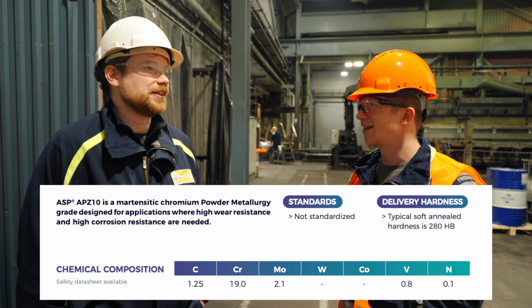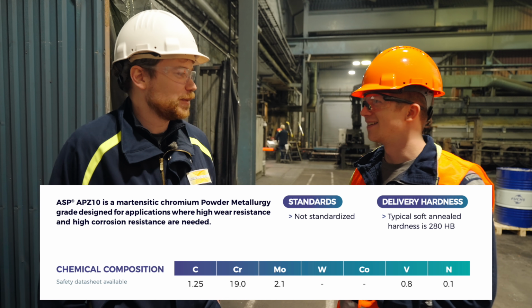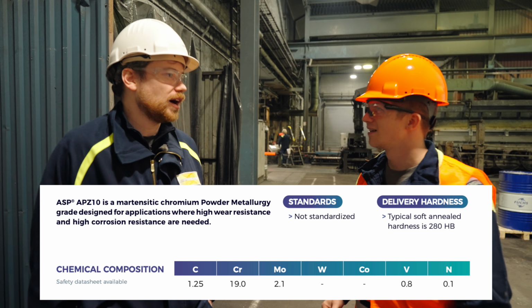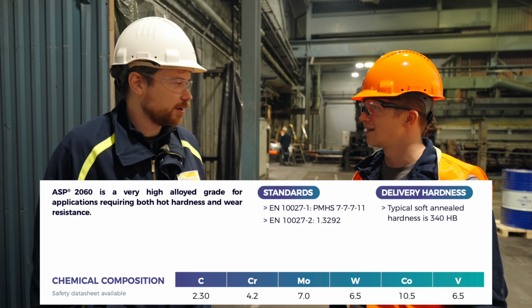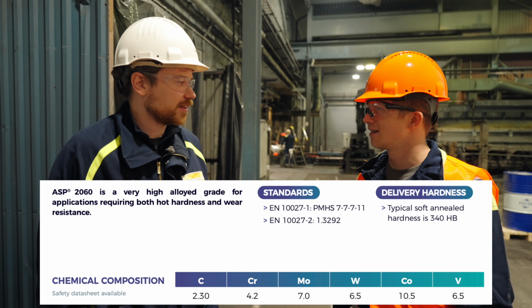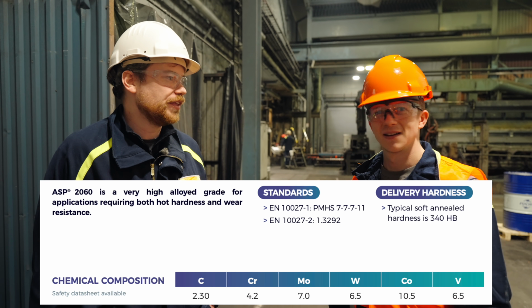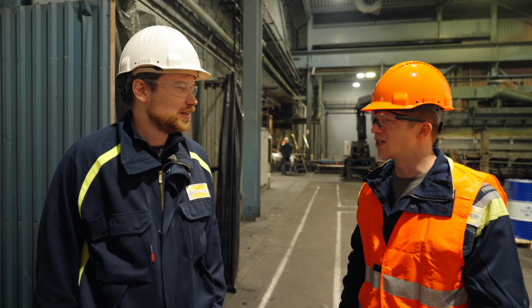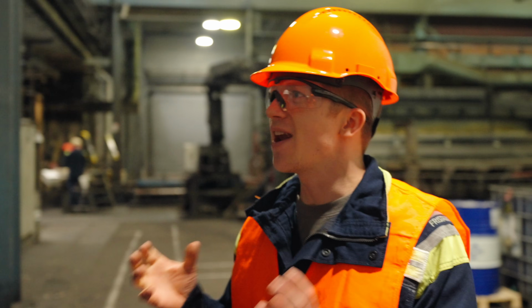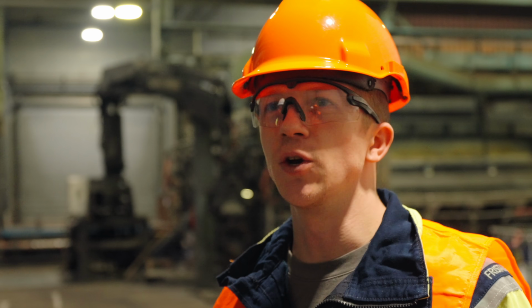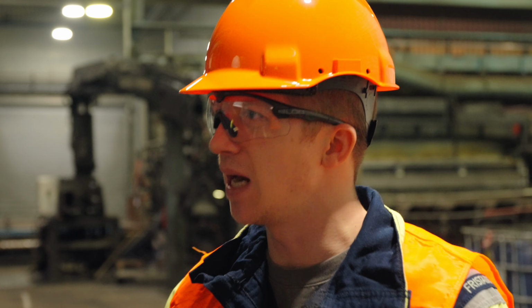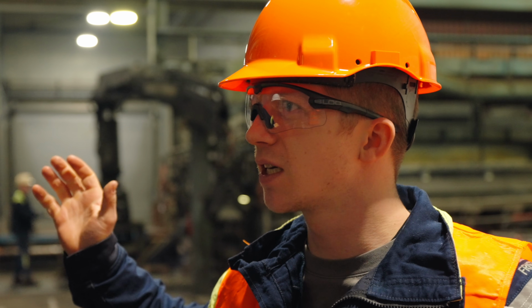Well, it's basically the highest alloy steels made in the world. So, we're talking about up towards 30% alloying elements, 65% iron for the highest alloyed grades. And so, 30% of that bar of steel could be materials like tungsten, vanadium, molybdenum, cobalt. And that's just not conducive to traditional steelmaking techniques. If you try to make that through ingot casting, it would never work, basically.